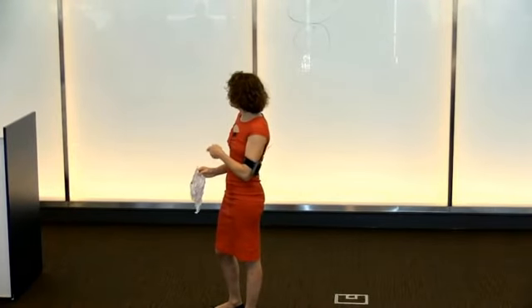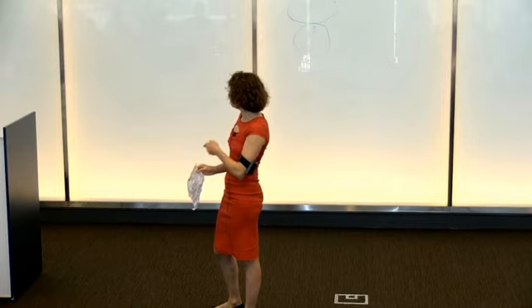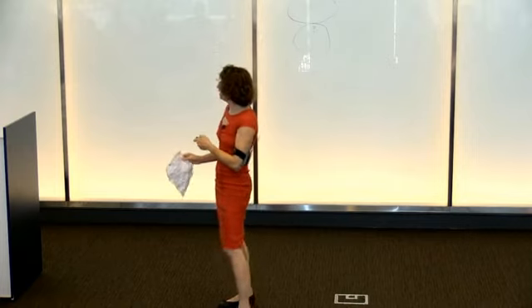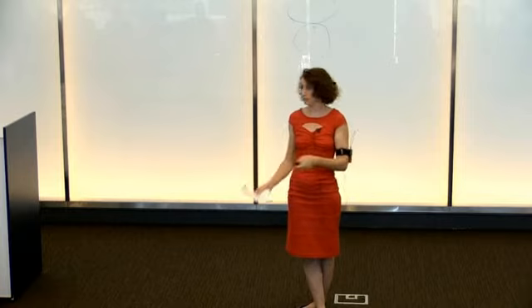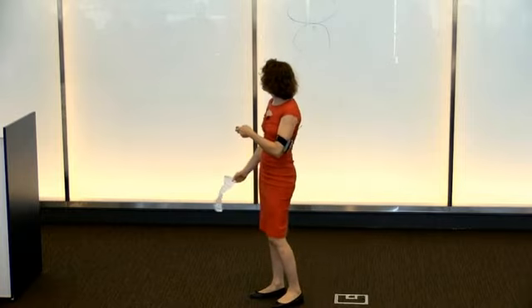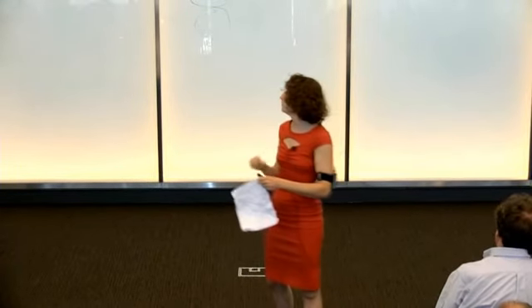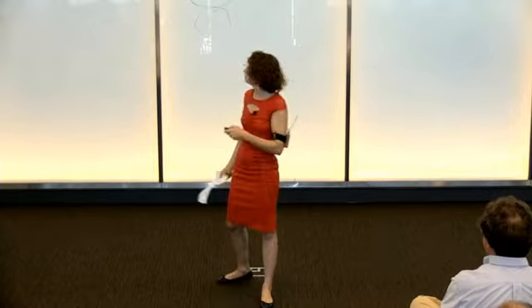And when you relax the energy of those sheets, you get shapes like this, which are, you can see, much more regular than the random lattice that I've shown you before. So all in all, you have only 3 different lengths. Just 3 numbers controlling the entire structure. You have a basis of hexagons, which are the shortest, and in the middle of the hexagons, you have longer ones.